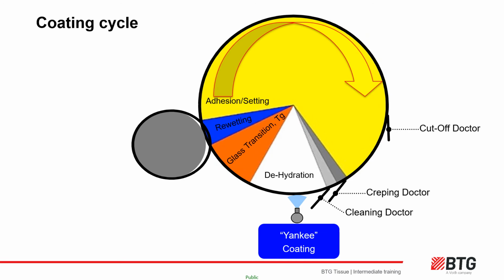The time it takes for the Yankee cylinder to rotate from the spray bar impact to the nip is called the coating dwell time, and is an important consideration in how quickly the spray water evaporates and where the coating becomes tacky. Machines will have different dwell times, and the same machine can even have different dwell time with any significant changes in Yankee speed.